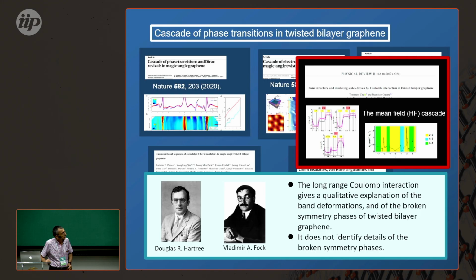Yeah, it's a feature associated with the non-homogeneous distribution of charge, the existence of a finite charge distribution away from half filling, and moreover, this charge distribution depends very much on where in the Brillouin zone you are. This is a unique feature of the flat bands in twisted bilayer graphene and related materials. That doesn't happen with the Hubbard model, for instance.